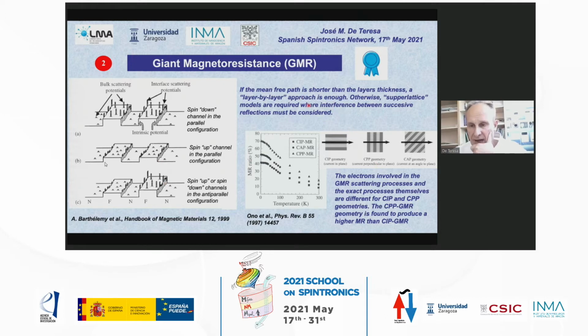Another point to highlight is that this simple, let's say, layer by layer approach is true if the mean free path is shorter than the layer thickness. But if the mean free path is very long, then there are reflections at the interfaces and there is interference between the wave functions. And then you have to apply a superlattice model, which is even more complicated. So I have given you a few ingredients of the theory, but we don't have time to discuss in detail all these very subtle effects.